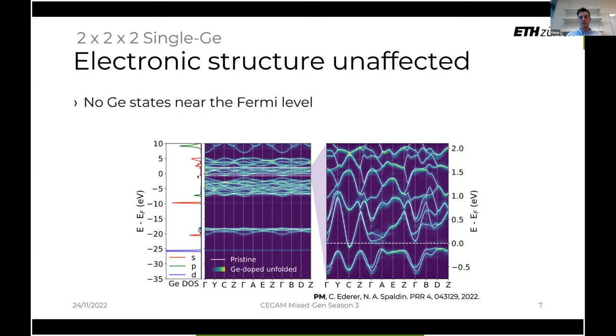And as you can see, the weight of the one germanium or two germaniums that we have largely sits way below the Fermi level, with very little hybridization with vanadiums and most hybridization with oxygens. The second thing to note is that in this monoclinic phase, which is what I'm showing here, we don't see that much of a change in the occupation of vanadium bands. So indeed, you can see that the band structure, the colored background, corresponds quite well with the white lines drawn.